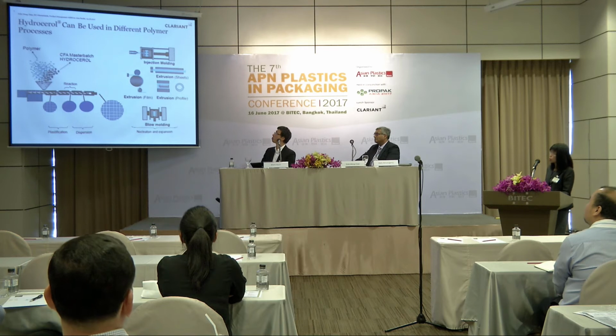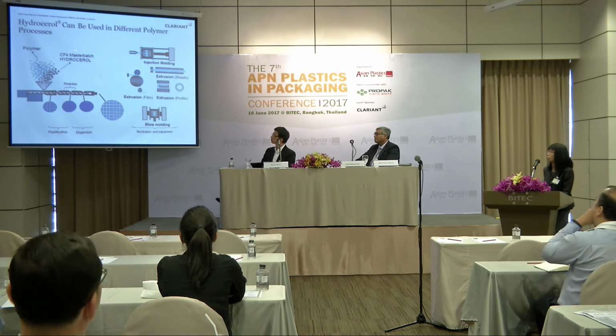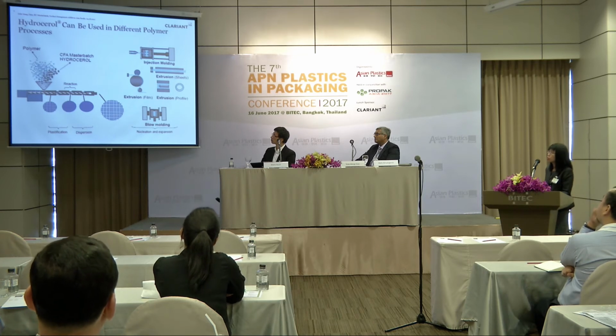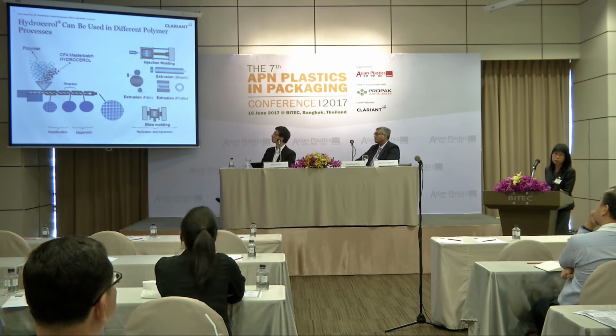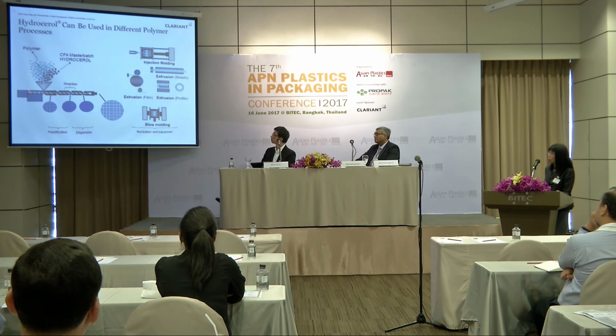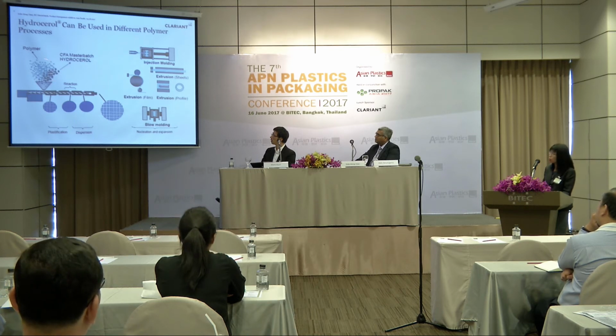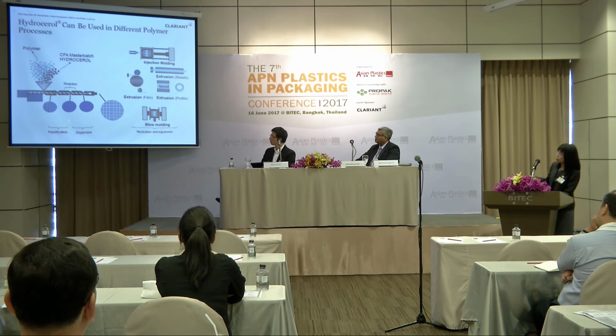So for Hydrocerol, a chemical foaming agent, it can be used in different polymer processes. It's very easy to use, usually in bottle production or packaging container production, whether it's using EBM or ISBM. So there's usually a feeding hopper to handle the resin and also color masterbatches. So this CFA masterbatch, the chemical foaming masterbatch Hydrocerol, can be dosed in the same way by blending with the polymer using the same feeding system, or using a side feeder system to feed into the extruder. So upon handling in the extruder, the reaction will take place here. You start with the plastification and then dispersion and then end up with a foam product.